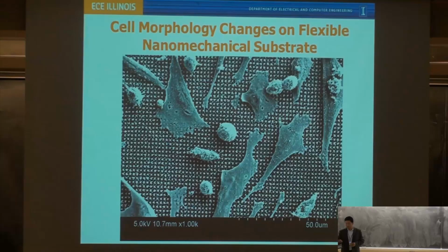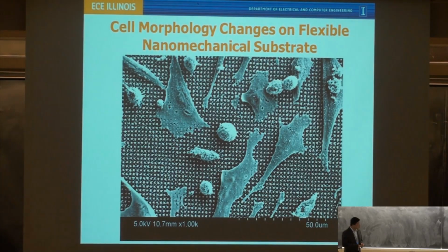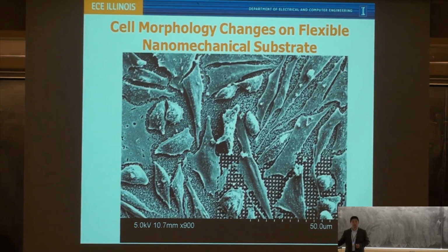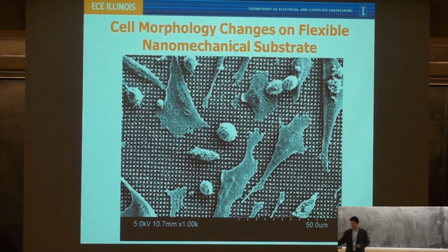So let me show you the next slides. You normally don't see cells look like this. Some cells really start stretching themselves apart into a very thin sheet, and the actual size of the cell sometimes becomes over 100 microns. They become crazily big, crazily stretched out. And if you look closely, they actually form a lot of anchor points. Are they still alive? Yes, they're still alive. Otherwise, they would not spread. They would just sit on top.